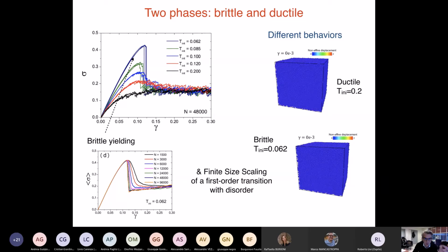Now, these are the fluctuations. We can also do finite size studies. So here is the finite size analysis at the lowest temperature, T init, 0.062, where you should expect to have a first order discontinuous transition. And this is what you find. If you average and you increase the value of N, you see that you go over a transition which is more and more abrupt, exactly what you expect for this discontinuous transition.